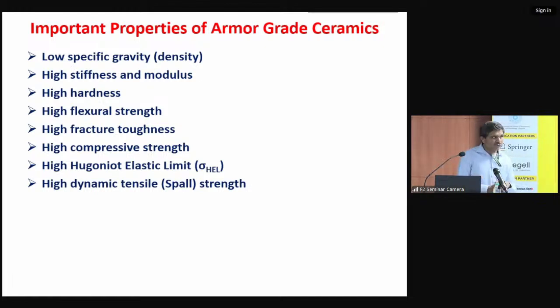Fracture toughness is also very important, because if the fracture toughness is low, the formation of cracks upon the hit of the bullet will be more. So that panel will not be able to withstand multiple hits of the bullet. So we should have high fracture toughness for the ceramic. The compressive strength plays a very important role, because we have observed the different grades of the ceramic. In fact, we have estimated the dynamic compressive strength by using the Split-Hopkinson pressure bar. If the dynamic compressive strength is lower than 2000 MPa, that ceramic will not perform well.